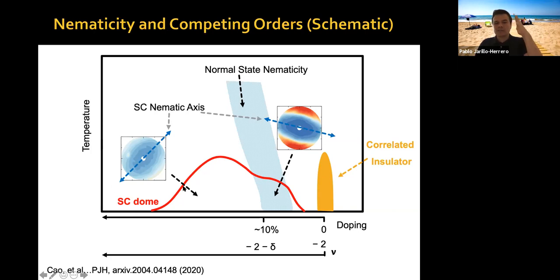So this ellipse is rotating a little bit, but then you reach the density region where you have normal state nematicity. You have another anisotropy, which is being set by another phenomenon, okay? And then your superconducting order parameter, boom, decides to align strongly with whatever order is competing here, and it's setting your anisotropy axis here, okay? And this is what happens.